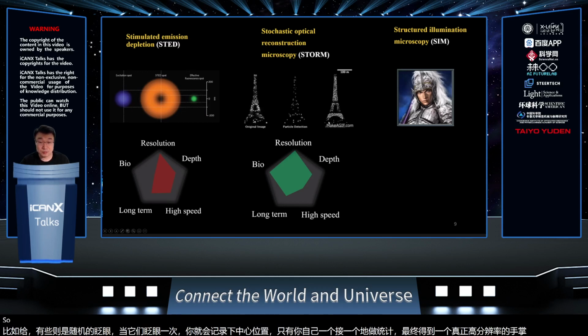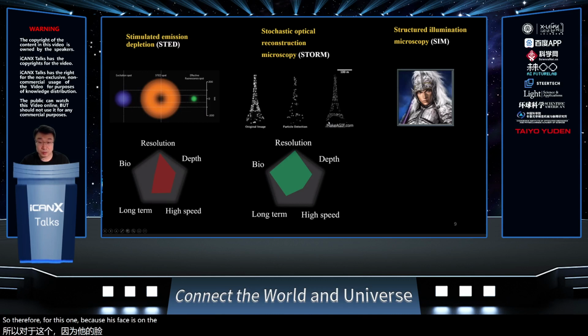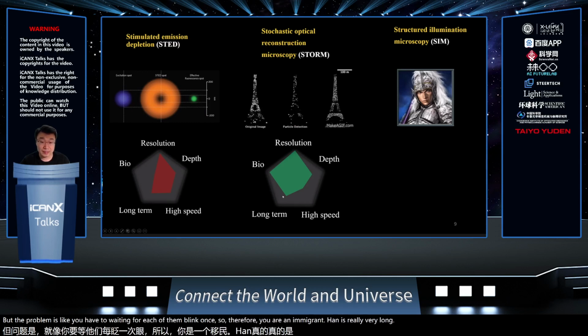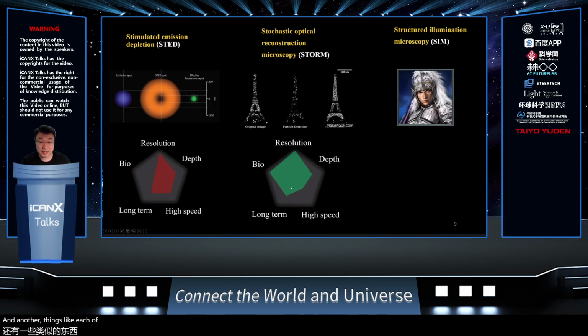Because this one is based on localization, the resolution is really high, even higher than STED. And it also has really good biocompatibility, because you just use a really small power. But the problem is you have to wait for each of them to blink once, so your imaging time is really long. And another thing is each of these dyes can only blink once or twice, so it doesn't work for really long term.